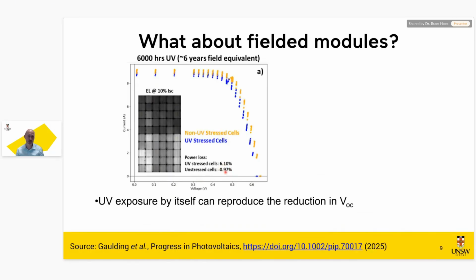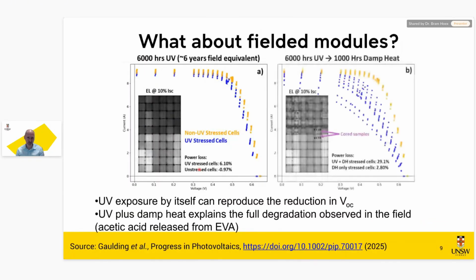and they saw that with UV stressing, they saw 6% loss, which is significant. And this was probably around 6000 hours, but like 6 years equivalent dose. So that's quite substantial. So 6% loss, we would not be happy with that. But if we do a combination of damp heat testing and UVID, we see a significantly larger loss. So this is a loss of 29%. And that's the combination of VOC and series resistance.